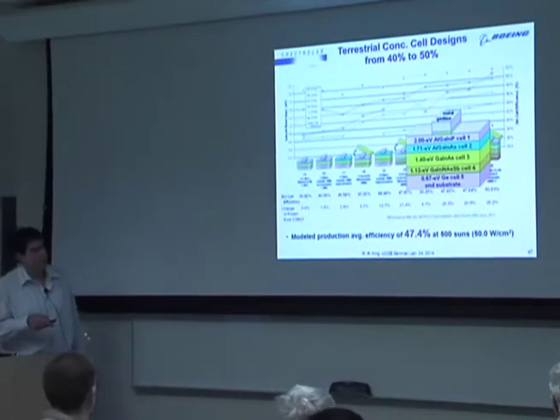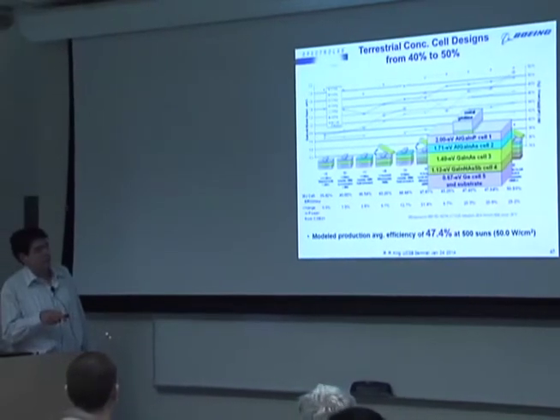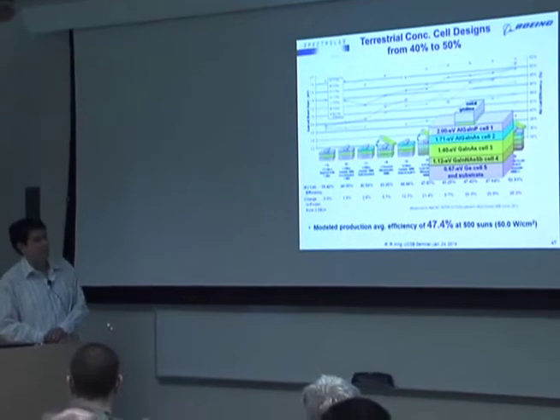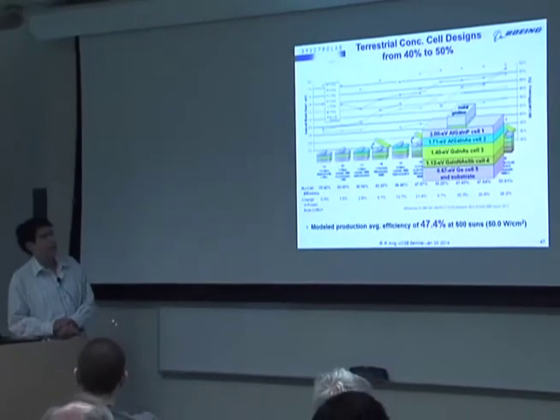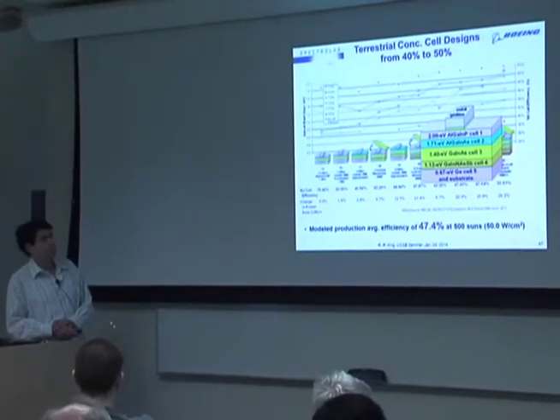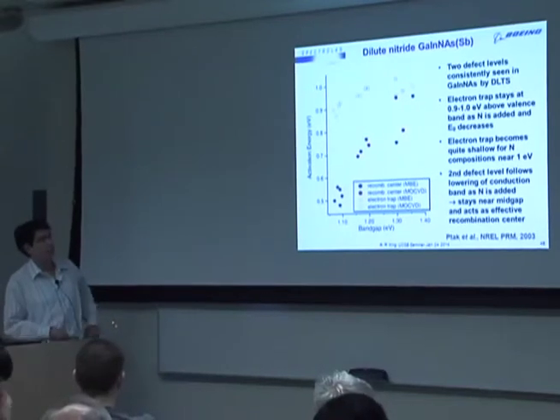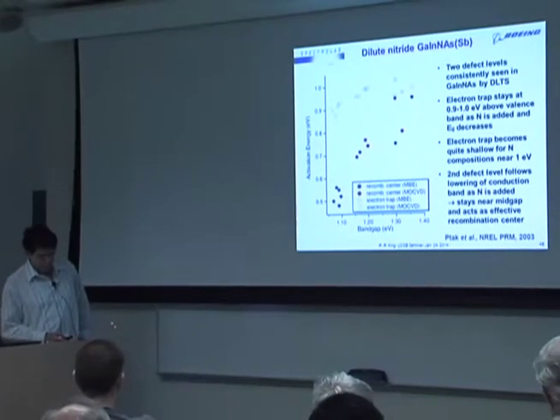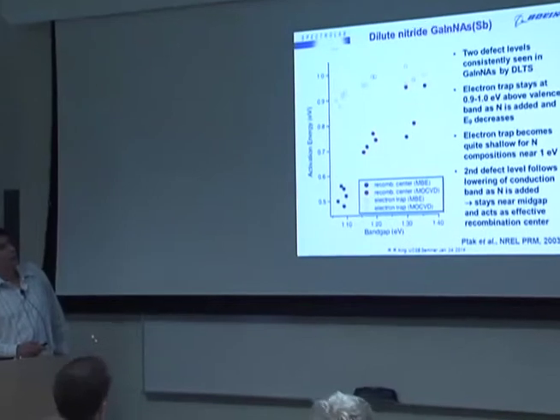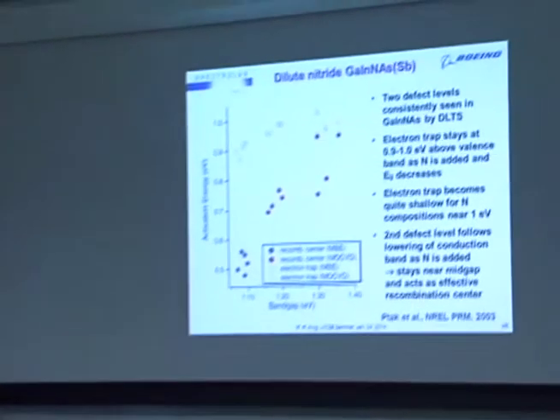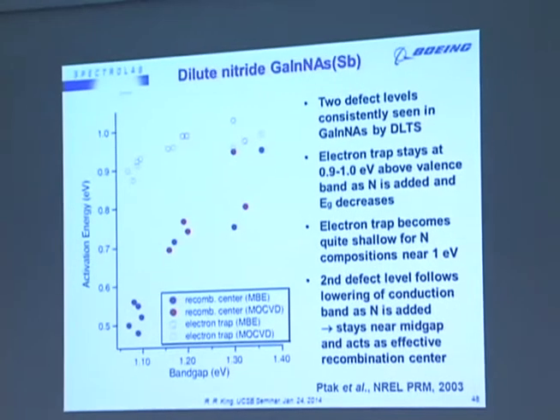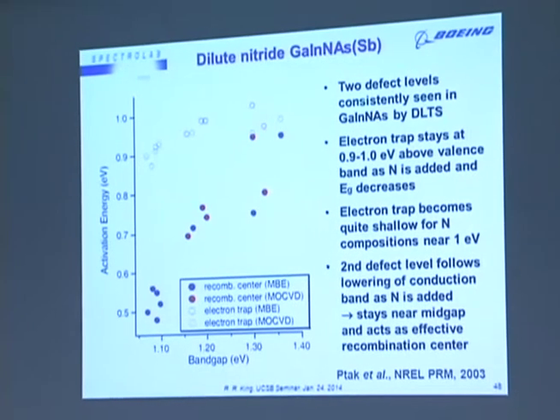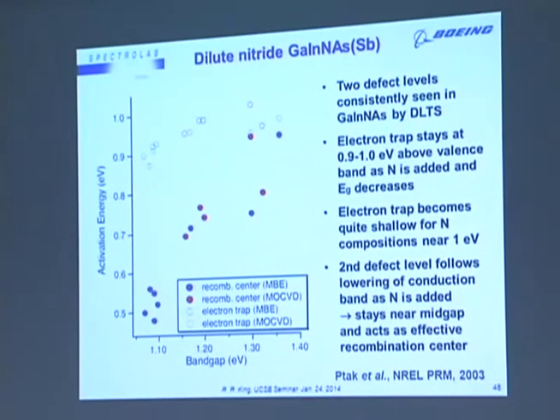Unfortunately, and I'll just point out that with a 5-junction cell of this type, we can reach a 47% efficiency, at least with realistic modeling. That's far from a theoretical efficiency. The problem is that this dilute nitride material has a number of defect levels which form in it. There's 2 defect levels that are seen consistently by DLTS.